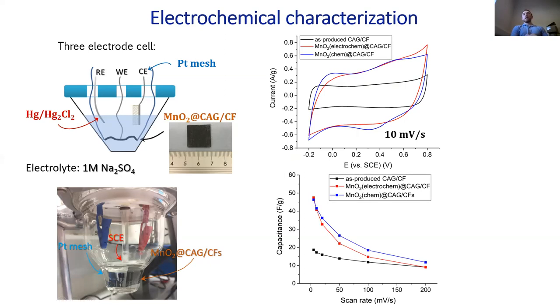system. And the overall area translated into the capacitance is actually increased significantly, although it decays at the highest scan rate due to a diffusionally limited surface redox reaction happening on the manganese oxide surface, which contributes to the pseudocapacitive contribution observed in our system.